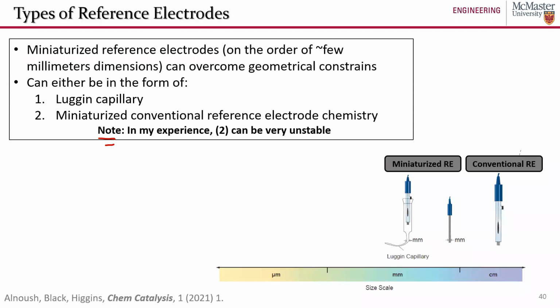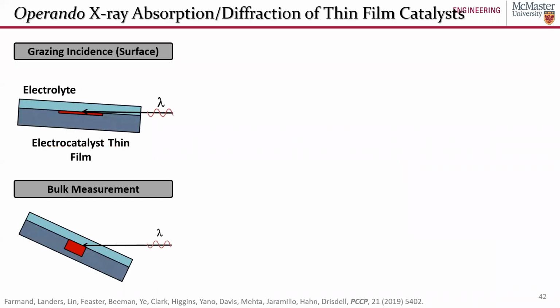So I talked a little bit about miniaturized reference electrodes, and so maybe I can just show an example of where these have been used for operando or in situ characterization techniques. We were developing thin film catalysts to try and gain fundamental insight into the electrochemical CO2 reduction reaction. When you're using a thin film, you've got 50, 100 nanometers of metal deposited on a substrate. But we were interested in these materials as catalysts, and we know that catalysis is a surface-based process. So we wanted to be able to characterize the surface of these thin film materials.